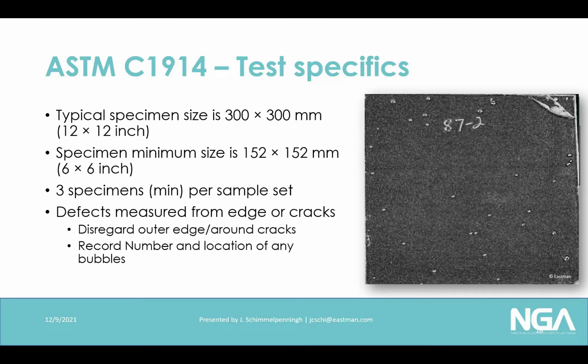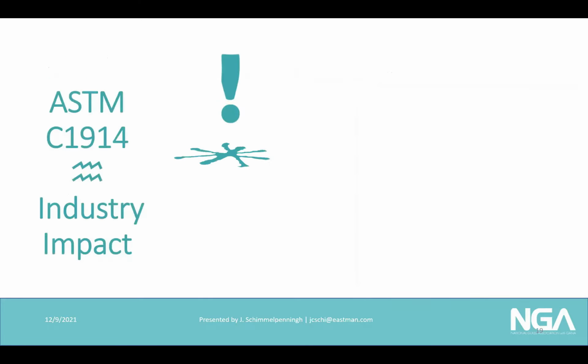One of the things that the test does allow, though, is it says you don't rate from the edge and you don't rate from cracks. And part of that reason is as you section or you cut apart to do the testing of these things, you can falsely destroy the edge. And so it gives you a leniency of about 13 millimeters to look at that.